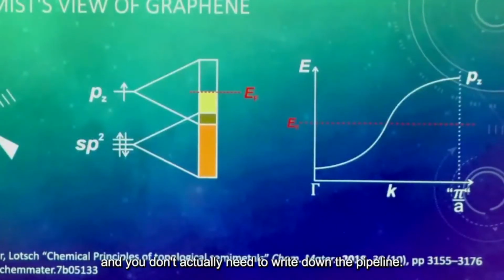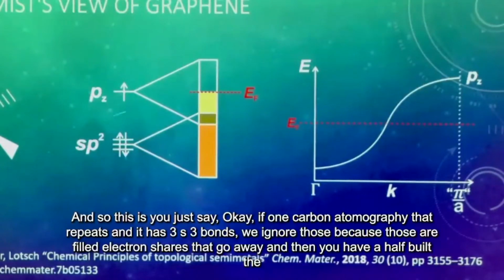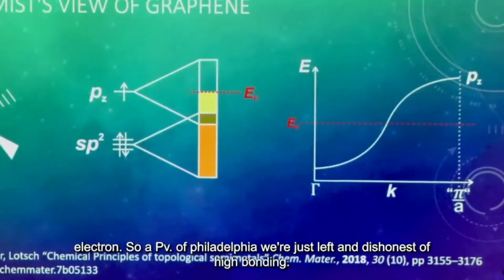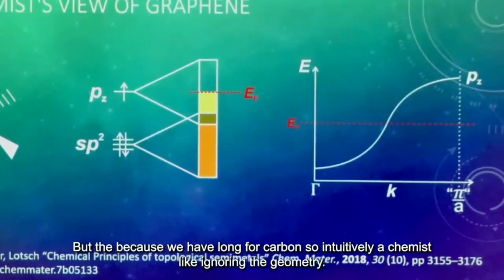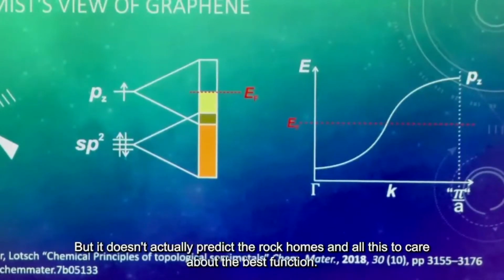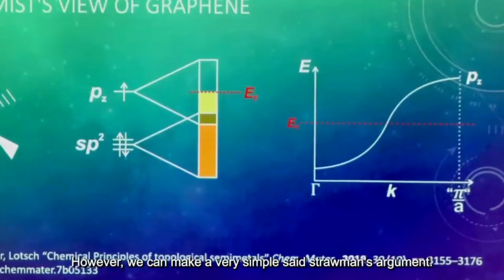So if you just say, okay, we have one carbon atom in graphene that repeats, and it has 3 sp2 bonds. We ignore those because those are filled electron shells that go away, and then we have a half-filled pz orbital, which is left and which forms the pi bonding. But it's half-filled because we have 1 electron per carbon. So intuitively, a chemist, ignoring the geometry for now, would sketch one band like that, which predicts accurately that graphene is metallic, but it doesn't accurately predict the Dirac cones and all the things you care about in the band structure. However, we can make a very simple, let's say, straw man argument.